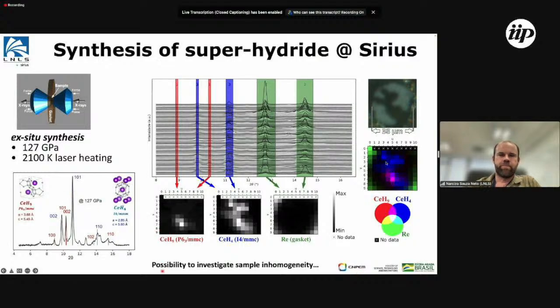But then when you look with X-ray diffraction, analyzing each point with a micrometer resolution of the X-ray beam going all around the sample, we actually proved that the superhydride phase is not uniform, not everywhere, but is more concentrated at one spot here that is about 3 to 5 microns, where we had the conditions, and this phase was formed here. And that is one thing that we can use Sirius for, to try to map and see what is going on, what are the phases that are possible in these microscopic samples as well.